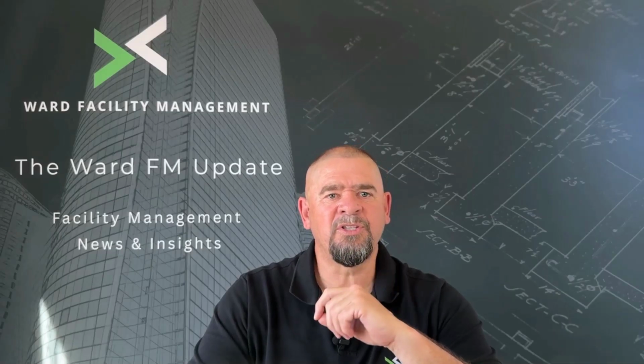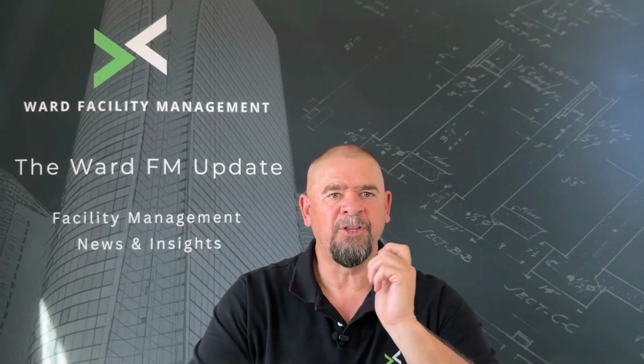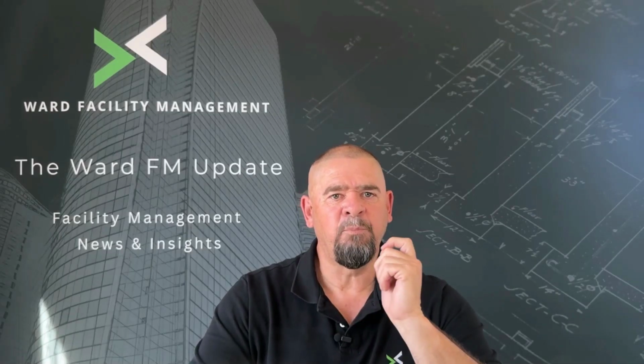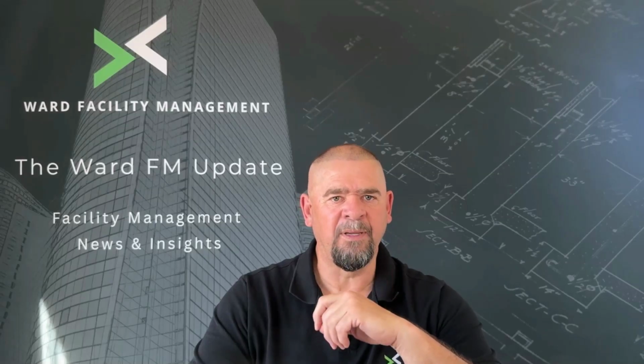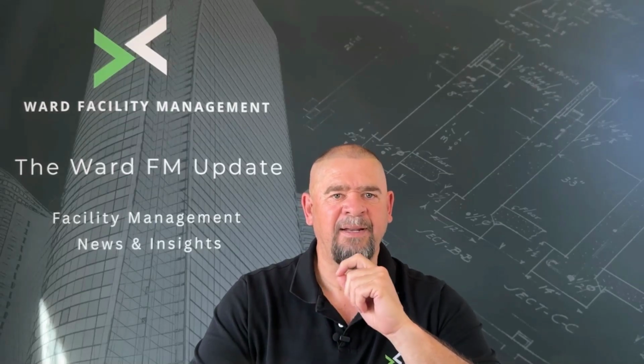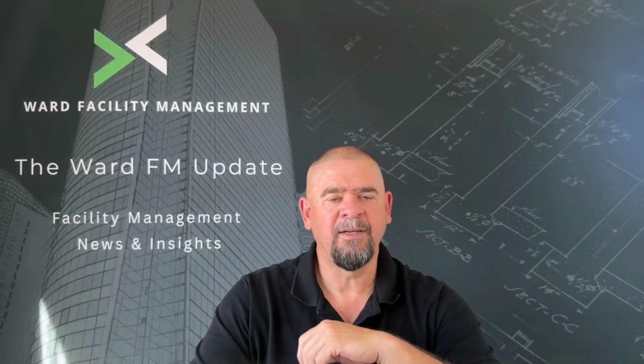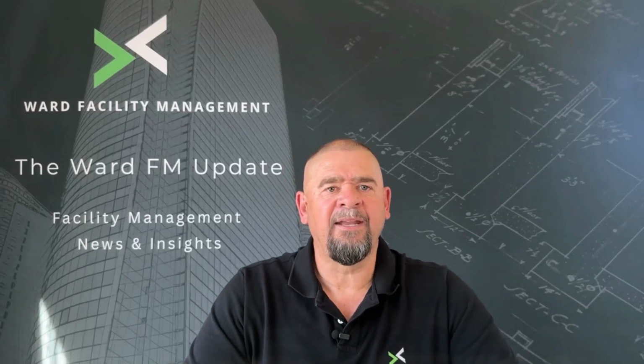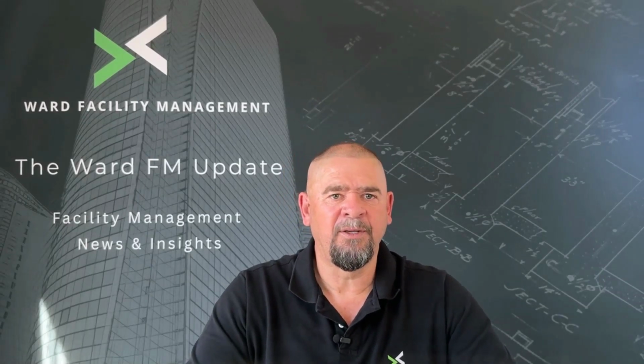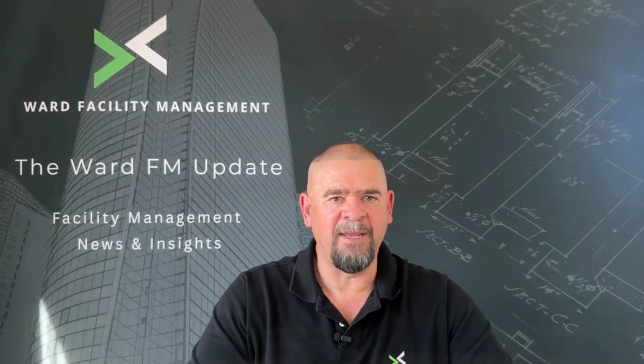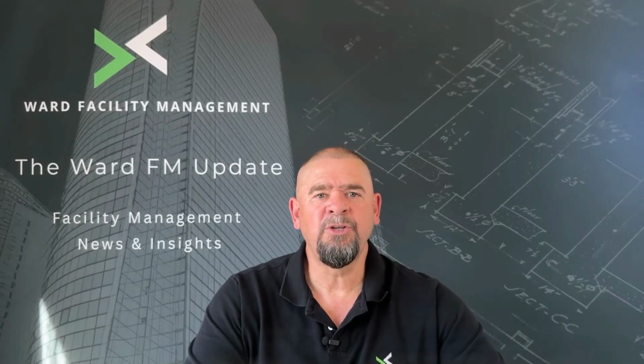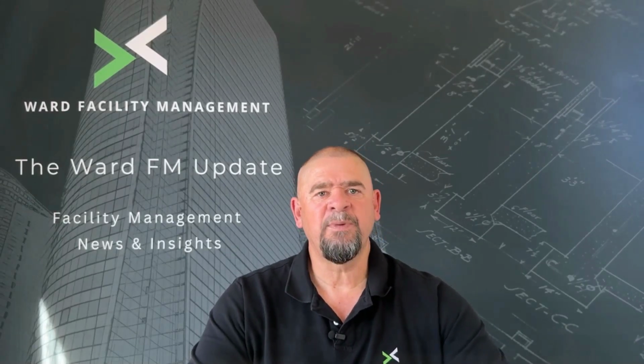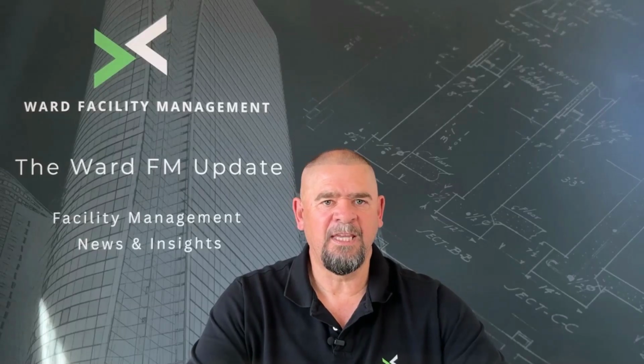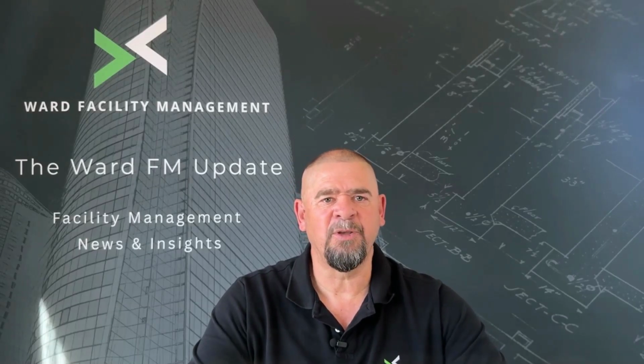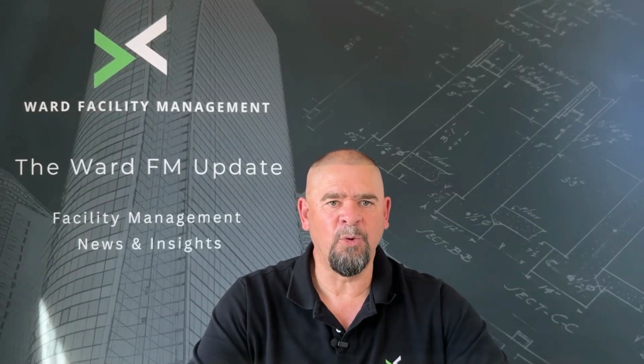We also need to consider which came first. Did the corrosion cause the leak, or did a poorly made joint begin to weep, leaving the connection damp and allowing corrosion to develop? A very small leak can remain unnoticed for a long time. The moisture evaporates, but the minerals and corrosion products remain behind. As the joint continues to wet and dry, the deposits become progressively more visible. Eventually, the joint deteriorates to the point where the leak can no longer be ignored.